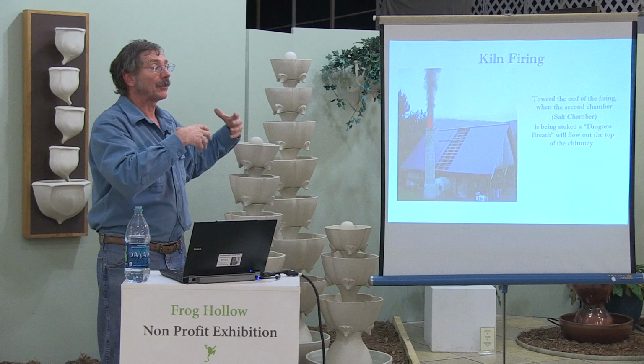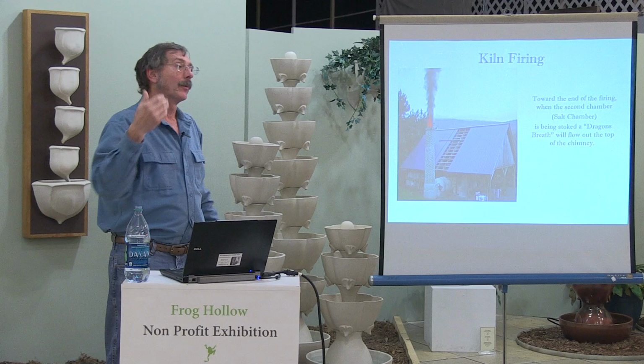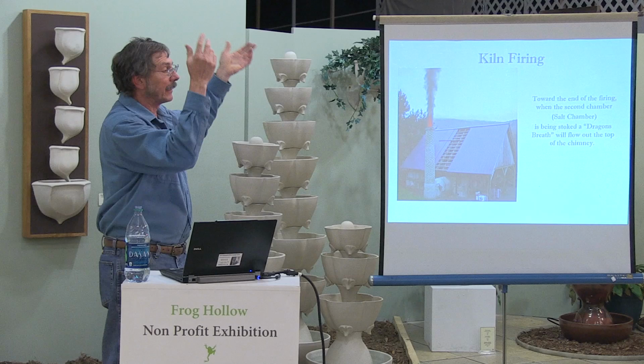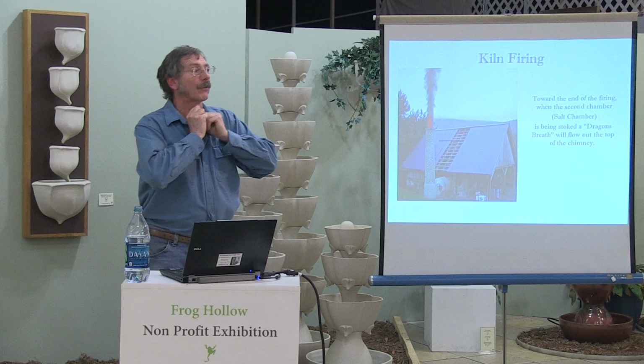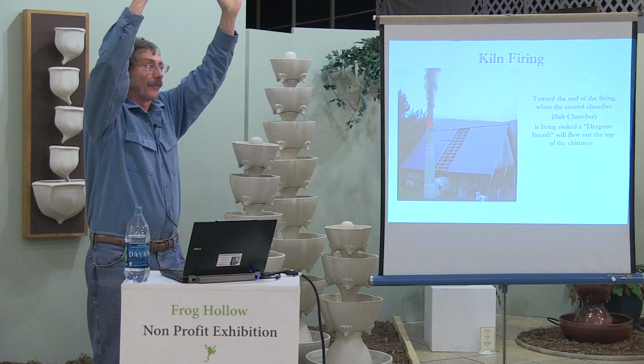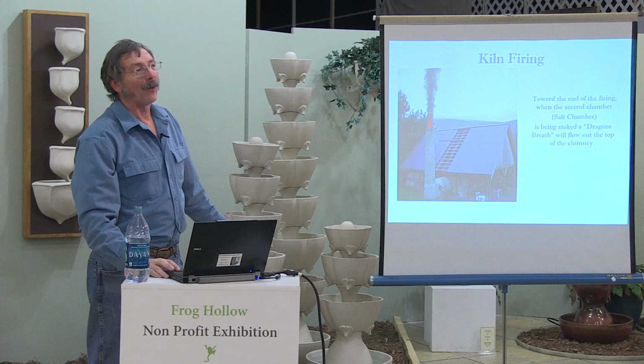you're 12 feet closer to the chimney at that point. So when you're stoking the back chamber, you start to get what they call a dragon's breath out the top, because the flames are basically 40 or 50 feet long. And when they come up and all these unburned gases finally hit the oxygen, they'll combust. You'll have smoky gas at first, and then flames will shoot up for a few seconds. It's pretty cool to watch, but it's not why you fire the kiln.